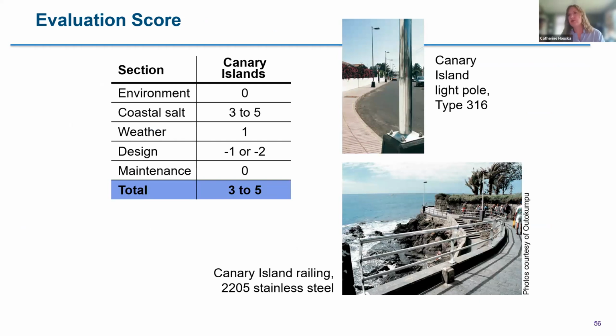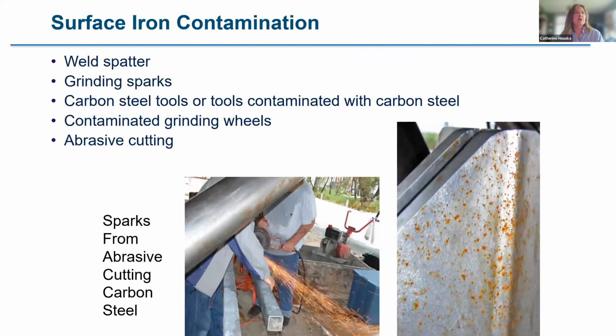Here's an example of one of our case studies, Canary Islands light pole versus railings. And oh, I didn't want to forget the possibility of iron contamination, which has nothing to do with anything else I've shown, but unfortunately happens too frequently. I can't believe they didn't grab my camera and break it when I caught them in the act. But those sparks got into the stainless steel and caused that lovely corrosion.